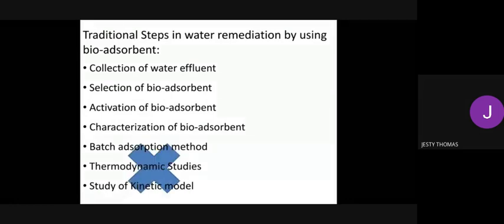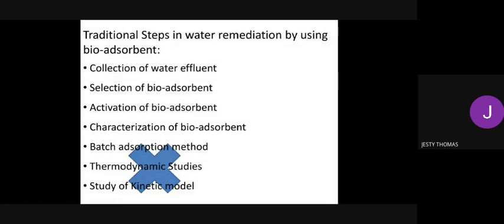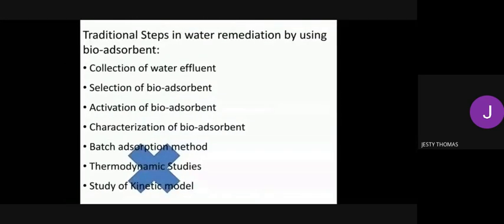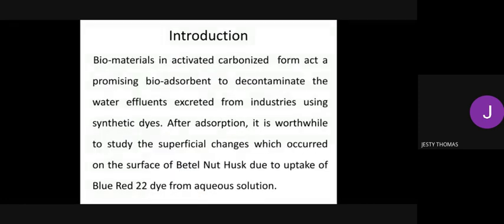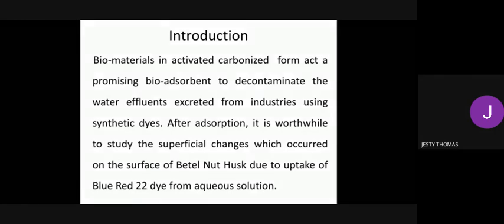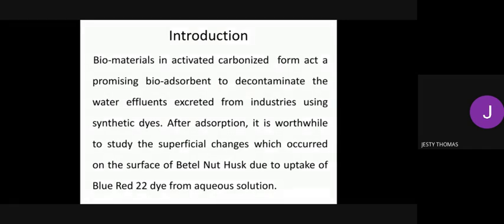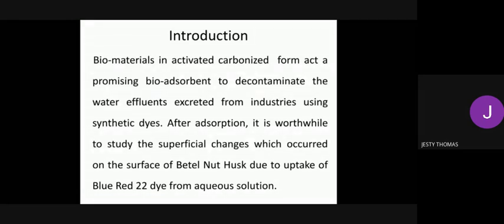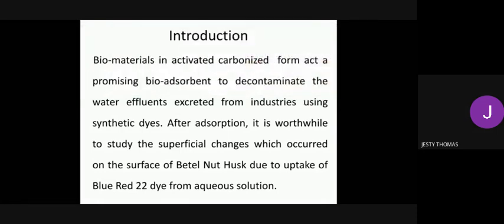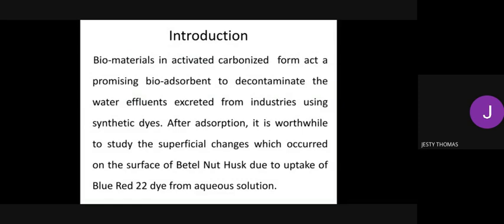But what we have done here is we have discarded the last three steps and we followed the first four steps. We characterized our bioadsorbent, then carried out our adsorption process, and we were interested in the changes brought about by the adsorption process. So this constitutes our introduction topic: we characterize our bioadsorbent particles, say that these are very suitable adsorbents, and ask what happens to those properties after the adsorption process. After adsorption, there are always superficial changes on the surface of the bioadsorbent. Here the bioadsorbent chosen is betel nut husk, and the dye is blue red dye 22.